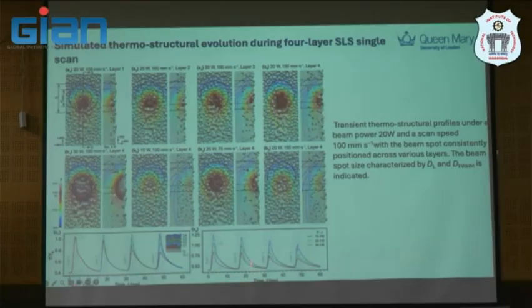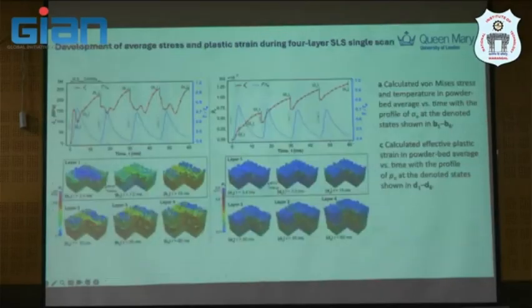So it actually dropped to about half of the melting temperature, not going to room temperature yet. What this tells us is that we can later relate this thermal field with the residual stress build-up profile. So we'll see this oscillated residual stress profile, based on the von Mises stress calculation here, and in different layers. So you will see how residual stress builds up as a function of layer.